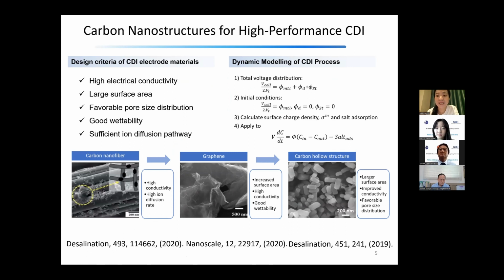Because the ions can be embedded into the porous structure, and also the pore size distribution, you don't want to make all the pores very big or very small, but a well-defined pore distribution, and also good wettability, so the water can easily go through the structure, and also sufficient ion diffusion pathways, so the ions can swim inside the structure. So those are the key factors to define the effectiveness of your electrode.